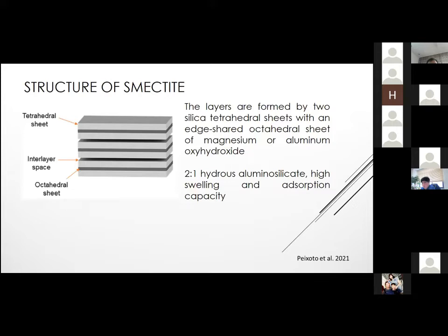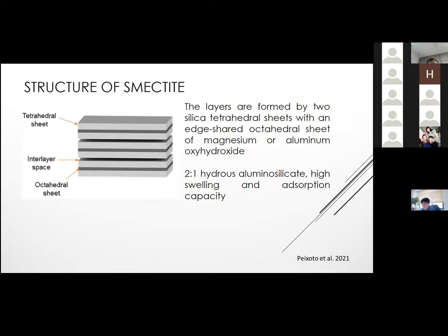Because of this structure, the smectite group has the capability to swell in the presence of water, which gives the material the ability to release the drug that has been absorbed inside its matrix. So when we introduce the clay into the water, it can swell and release the drug that we have loaded into these materials.